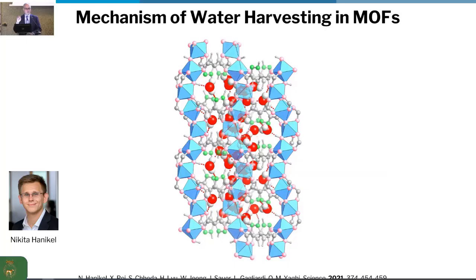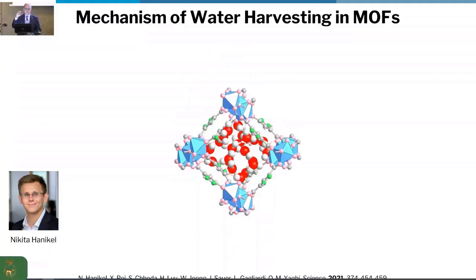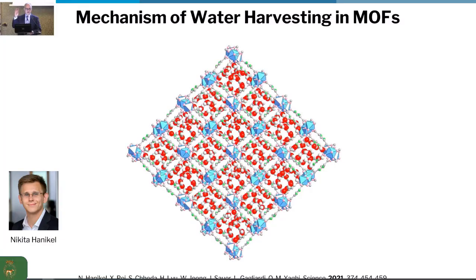So what I'm saying is that if you're a water molecule floating inside the pore, you're experiencing patches of hydrophilic and patches of hydrophobic. And this push-pull to water allows you to control how tightly water is bound inside the pore. That's why you could remove this water under ambient sunlight, just by heating under ambient sunlight. That is so important ultimately to commercializing this, because I don't need to necessarily bring in expensive power to remove the water. I could use waste heat, or I could use ambient sunlight. So these water molecules could be removed at 45 degrees or 50 degrees Celsius.